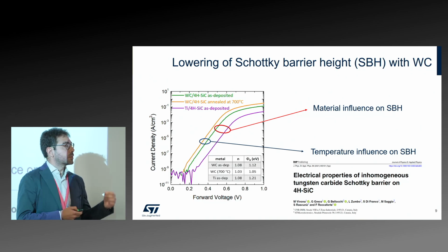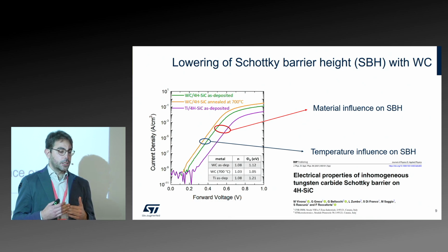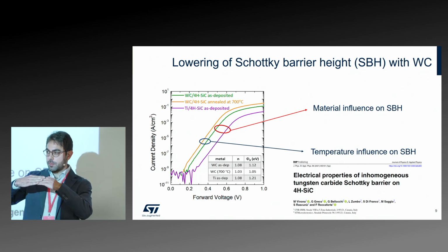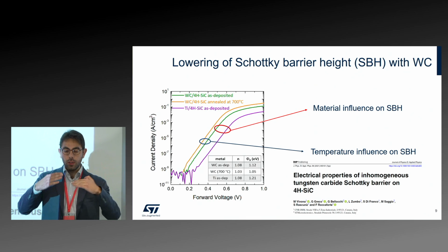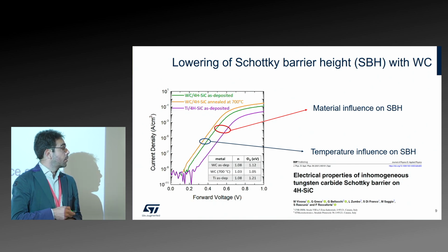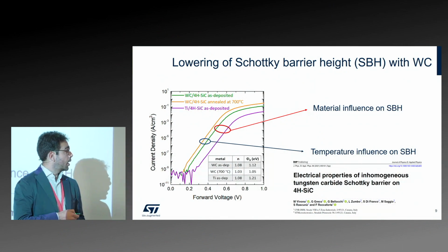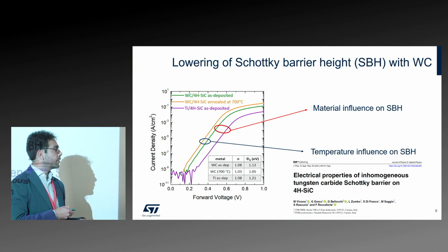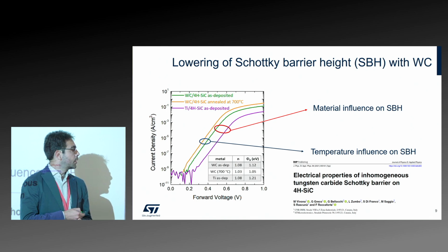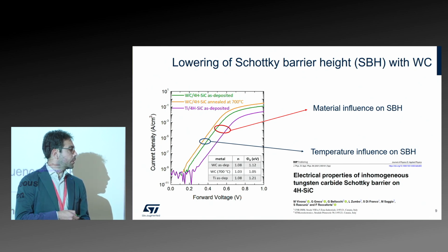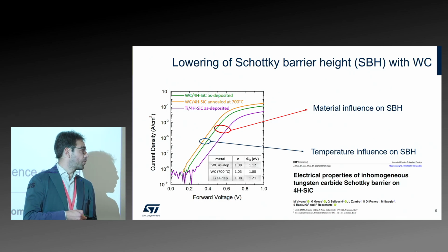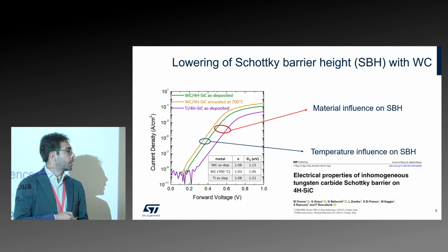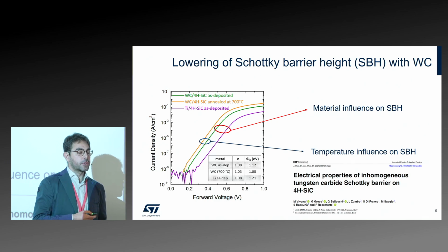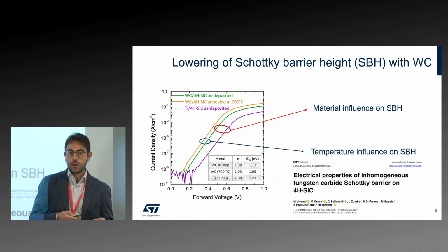This is something we can imagine, because each material has its work function, and if I couple it with my semiconductor, then depending also on the Fermi level, I can modulate the Schottky barrier height. But we combine not just the materials but also the process, so we started to anneal the materials, and again I observed a shift to the left side of the plot. That means another gain of 50 millielectron volts in Schottky barrier height, and that means, as I said, a gain in efficiency.